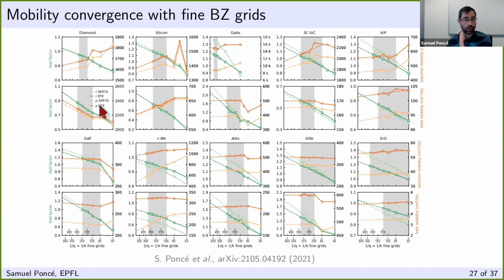And so what you can observe, in orange and in red, you have the SERTA and the iterative mobility given here for all of those materials. And in green, you have the SERTA and the BTE Hall factor. And what you can notice is that on an inverse grid size, those quantities are linear and they do converge, but they converge linearly. This can be shown and it's linked with the implementation in EPW, because if you're using the rectangle method, you can prove that this has a convergence which is linear in inverse grid density. And so this is also sort of good news, because it's linear, we can extrapolate that to infinite grid density, and then we can have the final value extrapolated to infinite grid density.